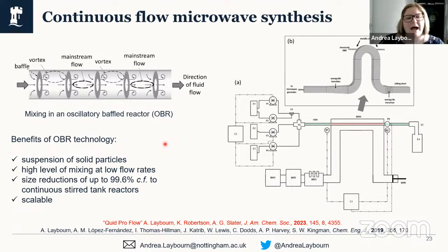So in our particular setup, we collaborated with researchers based at Newcastle University in the UK, and they have expertise in oscillatory baffled reactors. Now, for those of you who are not familiar with oscillatory baffled reactor technology, essentially it is a tube with regular intervals of baffles. You have an oscillating flow where your reaction mixture goes across the baffles, and as it goes backwards and forwards over those baffles, you get vortices happening, and so this is giving you efficient mixing of your materials. But the net flow is in one direction. So essentially, your flow looks something like backwards and forwards, but going in a net direction.